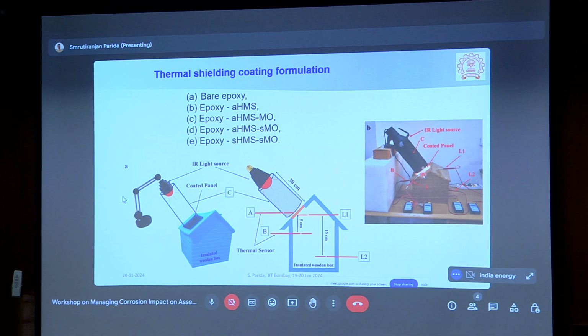And then when we irradiated, the incident temperature was about 60 degrees. Then we placed different thermal sensors at different locations in this model house, and we measured the temperature. The first temperature we measured is from L1, which is just below the coated panel on the opposite side. And then there is another point from where we took the temperature data, 15 centimeters below the metal panel, that is inside the house. The whole house is insulating. There is no chance of any external heating to this house because we have built it with a very insulating material, 16 mm thick plywood.